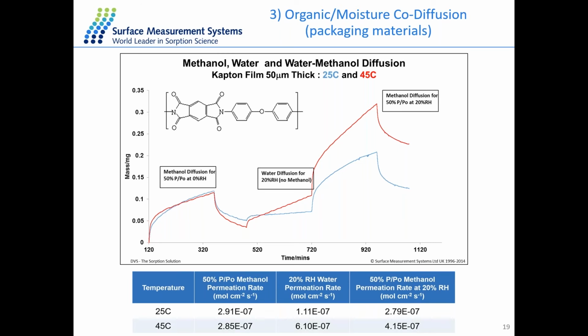And there is a huge difference in the plot as well. So this means the background humidity helps the methanol molecule diffusion at higher temperature. And here just demonstrates the potential to measure the influence of temperature and background humidity on the vapor transmission rate for some thin film or packaging materials with the help of the co-sorption method.